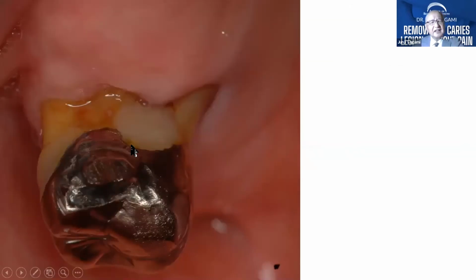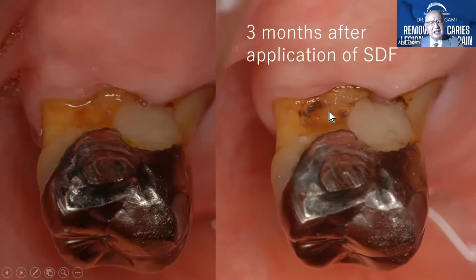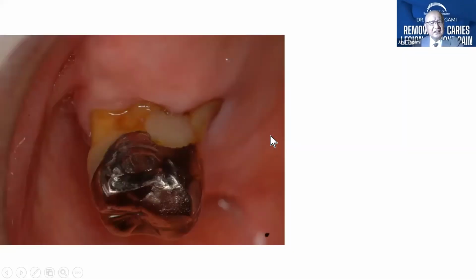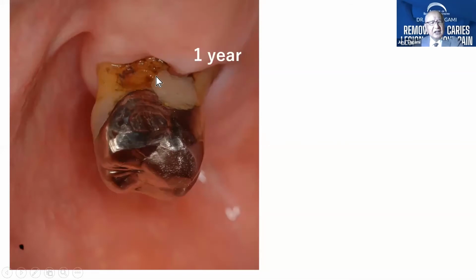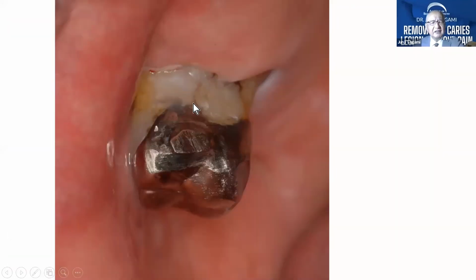In my clinic, I often apply the SDF in this kind of case. And after 3 months, some of the demineralized caries lesion is broken like this. I still followed up for 1 year. And after 1 year, I decided to remove this part and apply the filling like this. So the treatment of caries is now changing from the traditional method. Of course, the minimally invasive philosophy is very important to take care of the caries region. And after this, of course, the bonding procedure is very important, and also the filling technique is very important.